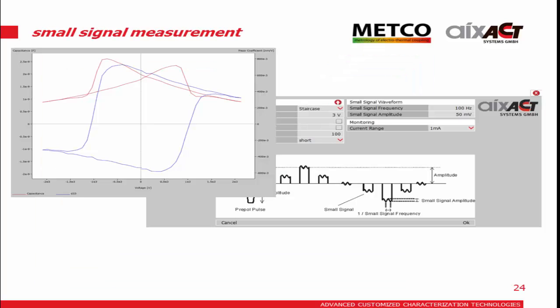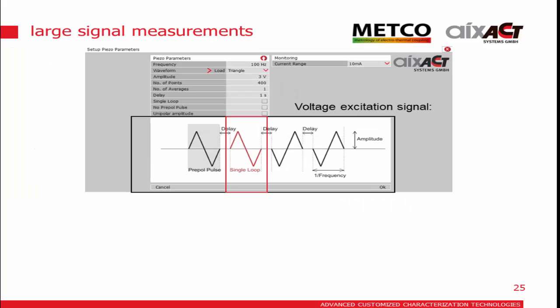So this is a typical small signal measurement, as I showed before. We apply DC steps with a superimposed AC field, but at a usually much lower frequency than in the resonance case. Then you can see the DC bias dependency of your D33. In the resonance measurement, you would only see the 0 volt point unless you have a special circuitry to be able to apply that DC bias. And for the large signal, the typical excitation is the triangular excitation.